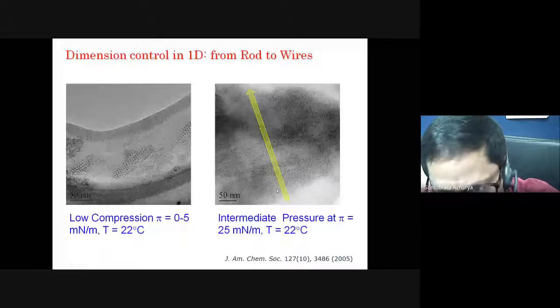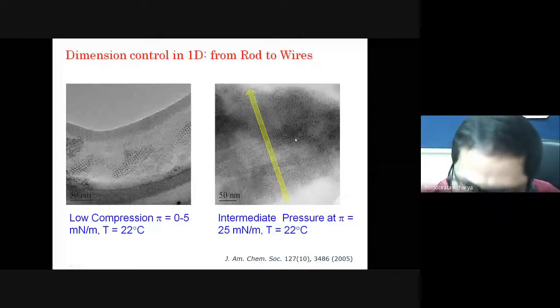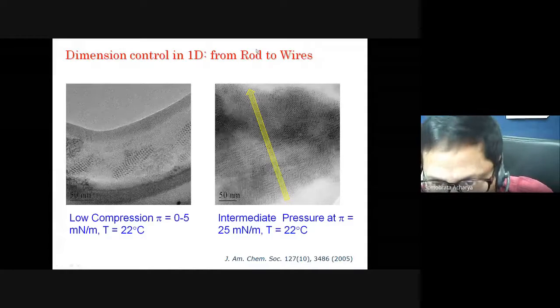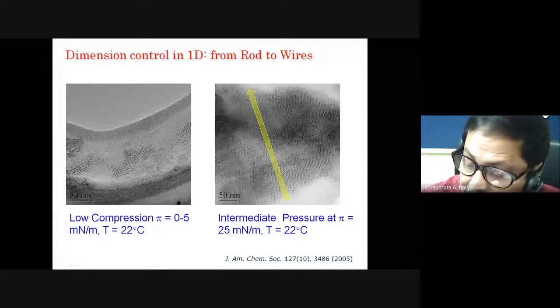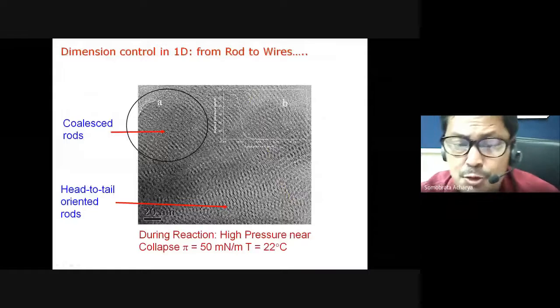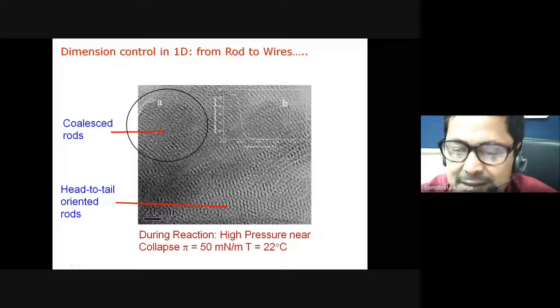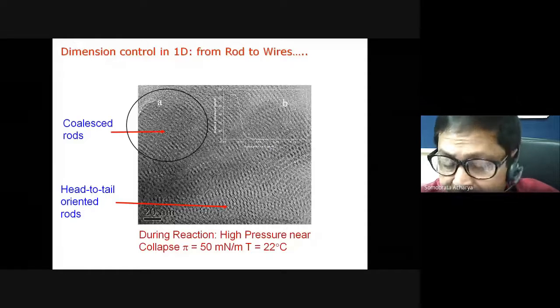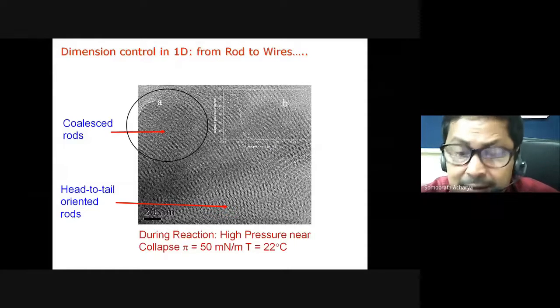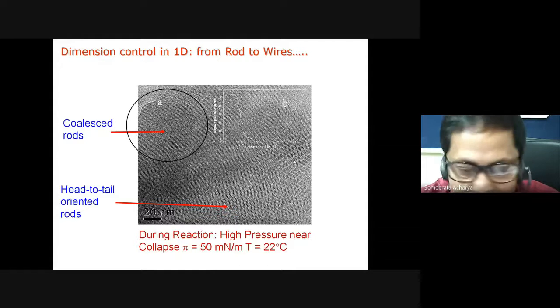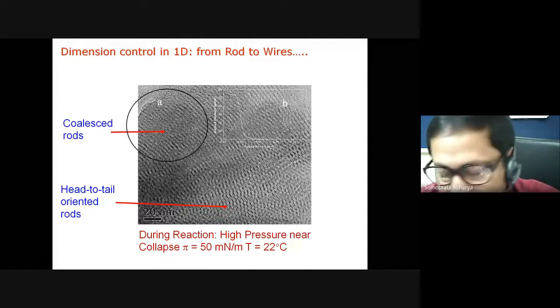compression. But eventually these domains are basically aligning to one particular direction. So this yellow arrow is showing the direction of the alignments, and you see that most of the nanorods are aligning along this direction of this yellow arrow. Now, if you keep the surface pressure on, you should not compress it further. You just fix the barrier at a certain surface pressure. Then you will see that some of these nanorods are basically coalescing into nanowires retaining the same diameter.